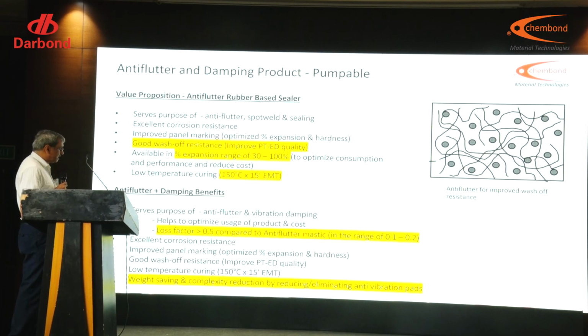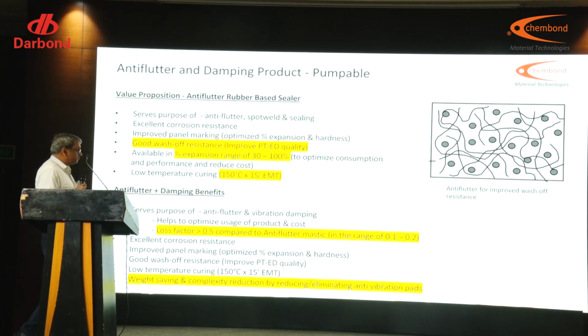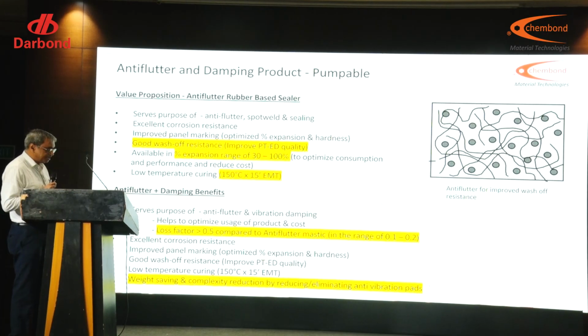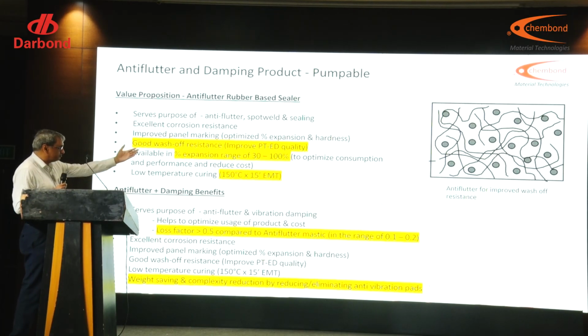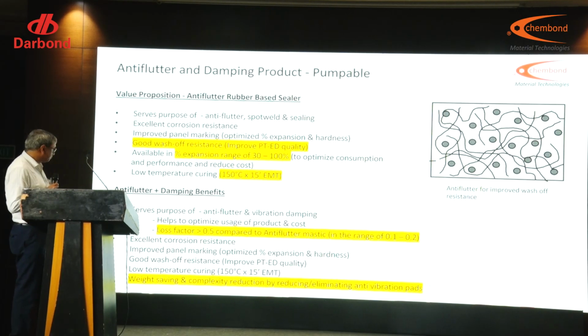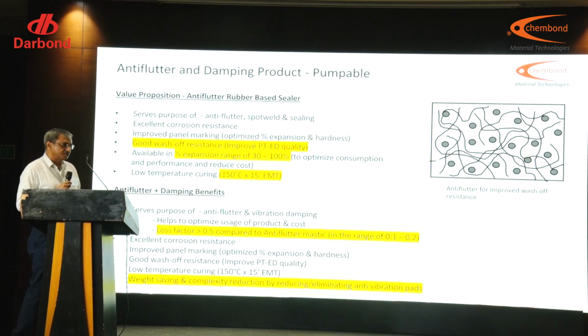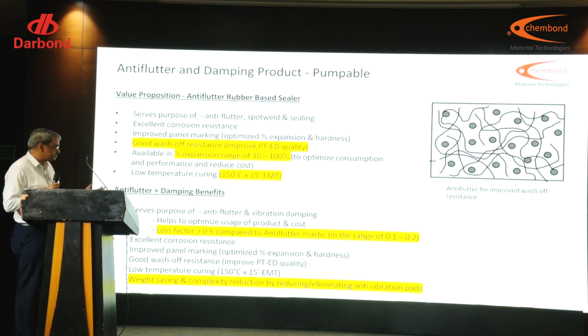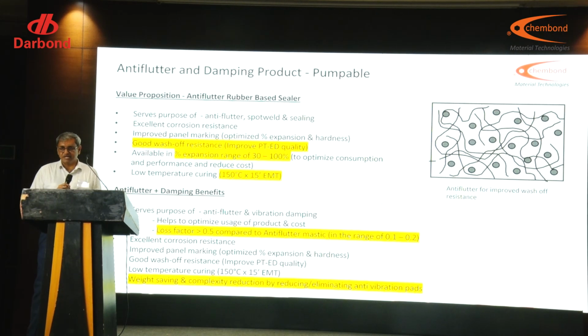This product is low temperature curing, and we can adjust the expansion as per requirement. Over and above, we also get anti-flutter and damping benefit, compared with conventional mastic, with good wash-off resistance and good damping properties, or you can say anti-vibration properties. This is a high damping foam product with a loss factor of more than 0.5 at any point of time, whereas conventional mastic has something around 0.2.